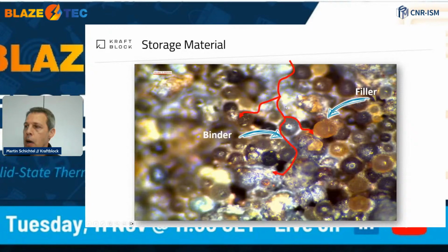We use those binders, which are the whitish lines in between the particles, to transport the heat deeply into the core of the material. If you go for an IR photograph, unfortunately I'm not allowed to publish it yet, but I think there will be a publication at the beginning of next year. If you charge the particle, split it in the middle and take an IR photograph, you can see that the shell is nearly as hot as the core. And that's what we need if we want to have very strong capacity and storage material use.